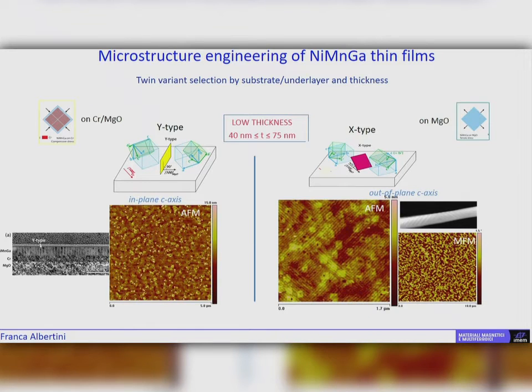For the film of the same thickness grown on MgO, when there is compression due to the substrate, we obtain another kind of twins that are the X-type, and in this case, the twins lie in this direction at 45 degrees, and also the magnetization points in and out of the plane. In fact, in the magnetic force microscopy measurement, we can detect some magnetic domain.